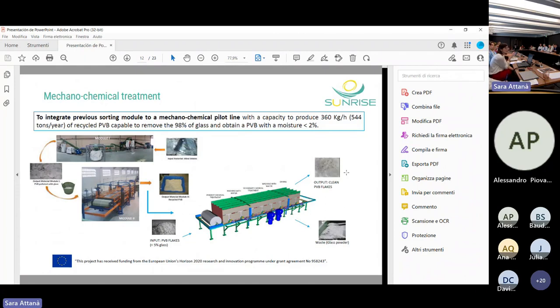How does it work? We have two steps. On one hand, we can make some mechanical conditioning of the waste. How we have been working in Lourederra is from full laminated glass, obtaining the PVB flakes and then cleaning. But we have also been testing PVB flakes directly from recyclers. So in some cases, this needs some additional mechanical preparation for removing more glass previous to the chemical steps, and also for shredding the PVB, which will be needed in the end. And then we have the chemical treatment.